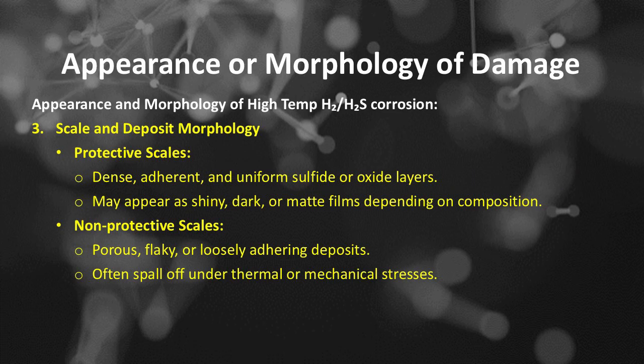The number 3 of the appearance and morphology of high-temperature hydrogen or H2 and hydrogen sulfide or H₂S corrosion is scale and deposit morphology. Includes: the first is protective scales, dense, adherent, and uniform sulfide or oxide layers, may appear as shiny, dark, or matte films depending on composition, and the second is non-protective scales, porous, flaky, or loosely adhering deposits. Often spall off under thermal or mechanical stresses.